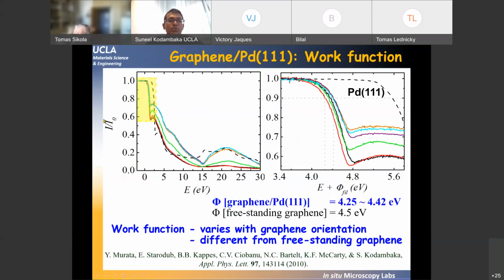Once you have those curves, then what you look for is the 10% drop in the intensity. These are normalized to the initial energy's intensity. And so the energy that corresponds to the 10% drop is the work function. But when we plot it, typically the raw data, the energy is the incident electron energy. And here we have the incident electron energy plus the work function of the filament, the LEEM gun filament, which normally we don't know, but one can get this for that particular measurement if you have a reference.